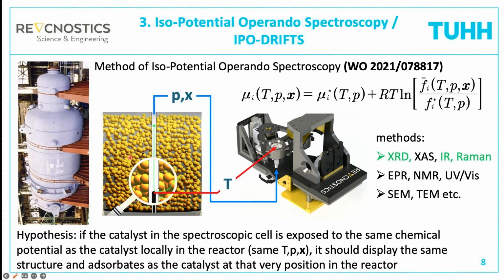You can go higher in temperature. I think there is also a lot of literature on high temperature IR spectroscopy. We have not done it. And the question is also how many molecules you will still have at the surface of the catalyst at very high temperature. When you do microkinetic modeling and calculate the coverages of molecules on the surface of a catalyst at very high temperatures, let's say 800 Celsius or so, there is very little coverage because everything is desorbing right away. So the question is if you would see a whole lot at very high temperatures.